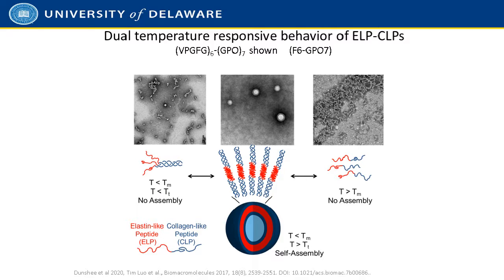We can make them, and then they're stable to injection if they're injected under conditions where they're stable, but they have a unique temperature responsiveness. At low temperatures, the elastins are soluble, but the collagen triple helix is intact. So what we see in the microscopy image, in this case just TEM, are these very small structures that are aggregates of an undefined sort, these mushroom-like structures that we have, or the triple helically folded conjugates. If we go from the center microscopy image to the right, you can see that there's a very different structure that we see.